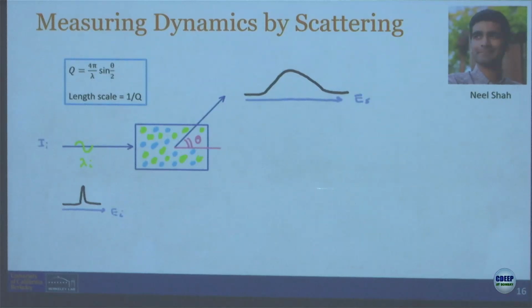I mean, this experiment requires a nuclear reactor at one side. The experimental chamber is about the size of this building, this room. And there in the middle is a little polymer sample with detectors all around, much like those little squares. Very imposing experiment. But it turns out that neutrons are only sensitive to hydrogen, because hydrogen atoms don't have a neutron. All other atoms have neutrons. And so when a neutron sees a lot of stuff, this quasi-elastic signal is completely telling you only about the motion of hydrogen.